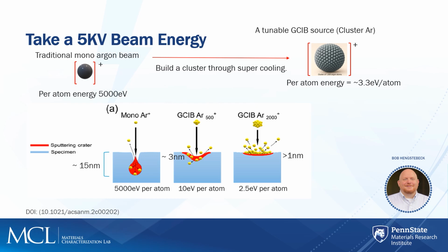If our information depth is on the order of 3 to 7, and we've damaged the material up to 15 nanometers, we may have changed that original surface that we wanted to look at. We've lost the chemistry, and that's actually normally what happens. And I'm going to show you an example of what that looks like. The new GCIB source works very differently.